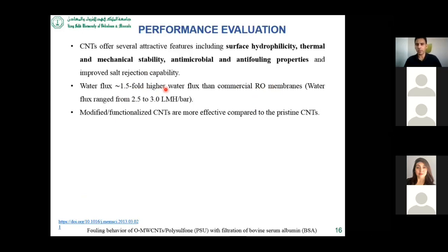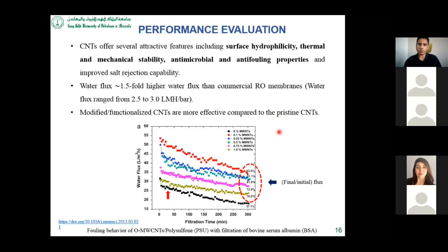Remember that the commercial RO membranes are currently dominating the water treatment as well as the water desalination market. So if you can provide some membrane that can provide the same flux or even higher, this is really a breakthrough technology. Then, as I told earlier, the carbon nanotube can be modified or functionalized, and it is found that if you modify the surface of the CNT, its properties are further enhanced, and they exhibit more fantastic properties compared to the pristine carbon nanotubes.